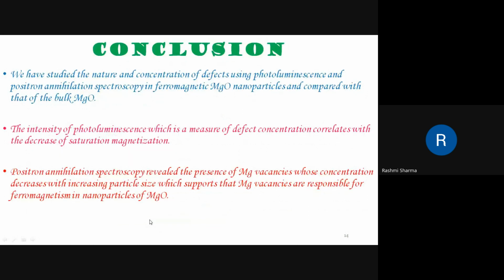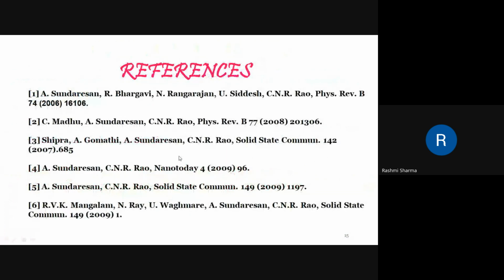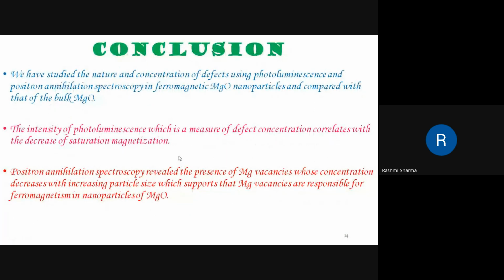So here I come to the conclusion of my topic. In this talk, we have studied the nature of concentration of defects using photoluminescence and positron annihilation spectroscopy in ferromagnetic magnesium oxide nanoparticles. Using the photoluminescence spectra, what we found is that as the size of the particle increases, the intensity of luminescence decreases. Positron annihilation spectroscopy revealed the presence of magnesium vacancy. Magnesium vacancy concentration decreases with increasing particle size. This is all about my presentation.